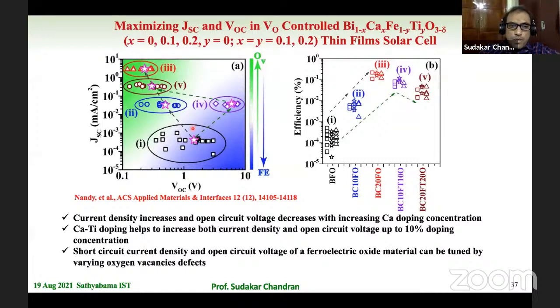And also, as you can see in this particular picture, if you want to get a high open circuit voltage, you should have a ferroelectric nature, and that's what this blue shading shows. If you want a high short circuit current, you should have large oxygen vacancies, and that's what the green curve shows. So both are in two different directions. So you need to find an optimized condition, because if I keep on increasing the oxygen vacancy beyond a certain point, it goes that side.